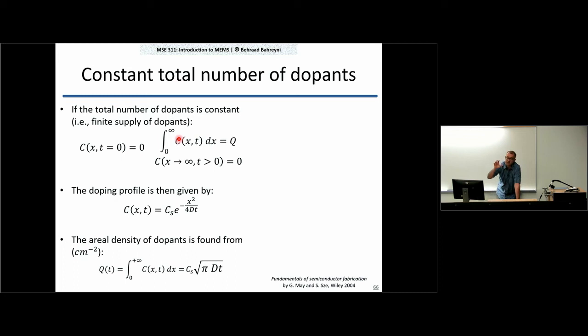You're just redistributing them. If you go through that and solve the equation, you will find out that the concentration is given by this expression. It's more like a Gaussian. And at the end of the story, the areal density is given by this expression. So whatever CS, whatever Q you have at the beginning, it's going to be CS times square root of pi dt.